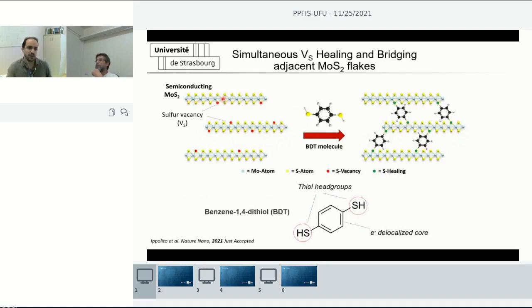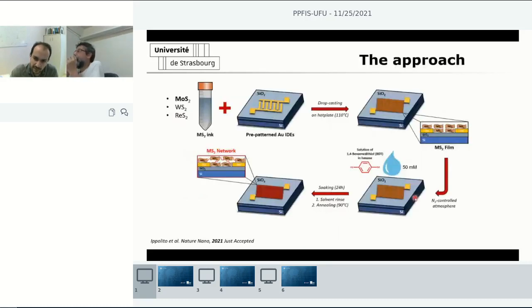So we took our molybdenum sulfide semiconductor, which has sulfur vacancies, and we functionalized it with this molecule called BDT, benzene dithiol. So it's a benzene core, with delocalized electrons, and two thiol groups to not only heal the vacancies by substituting the vacancies with these thiol groups, but also bridge two adjacent, close flakes.